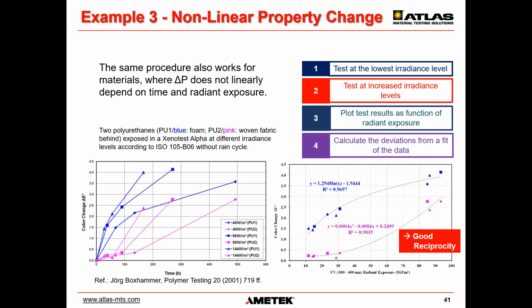and radiant exposure. It doesn't have to be a linear curve. This is demonstrated in a study of two polyurethanes, PU1 blue, a foam, and PU2 pink, a woven fabric with a woven fabric behind, exposed in a Xenotest Alpha at different irradiance levels according to ISO 105-B06, the so-called hot light fastness test that doesn't have any rain cycle in it. You see, it also works well. If you plot time to radiant exposure in the UV, you also get these not into a straight line, but into one curve that you can fit.